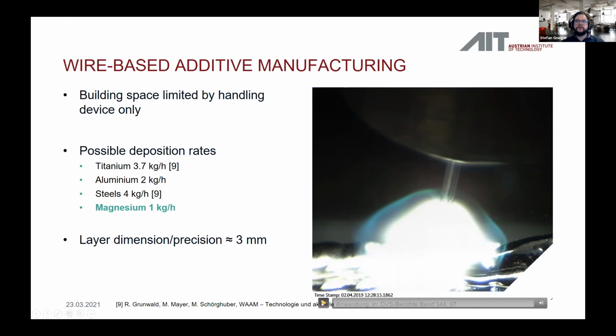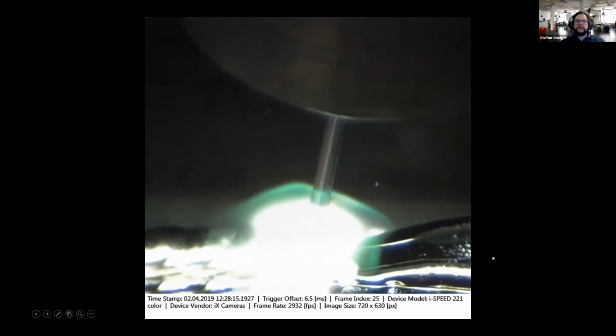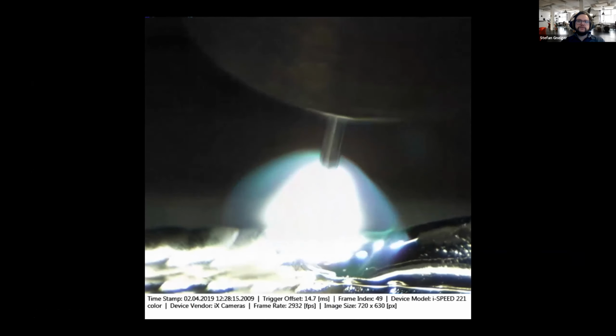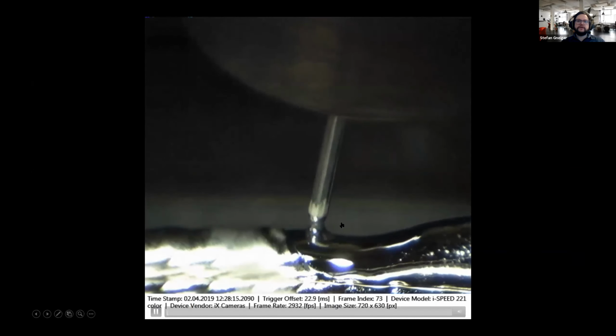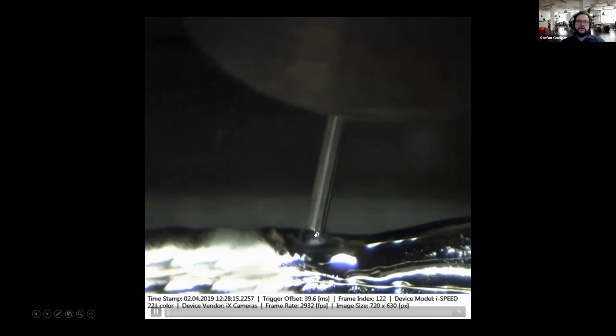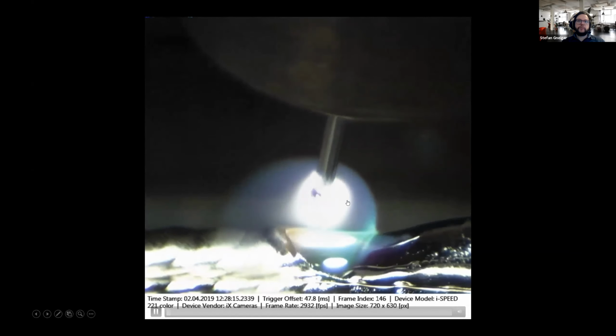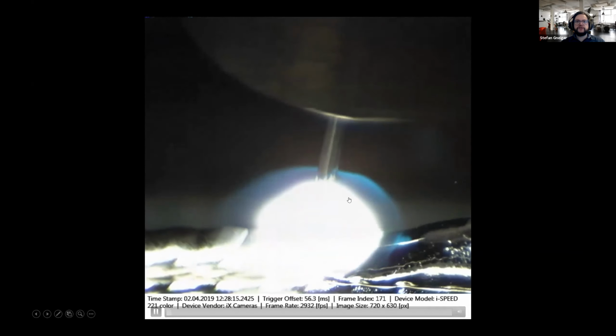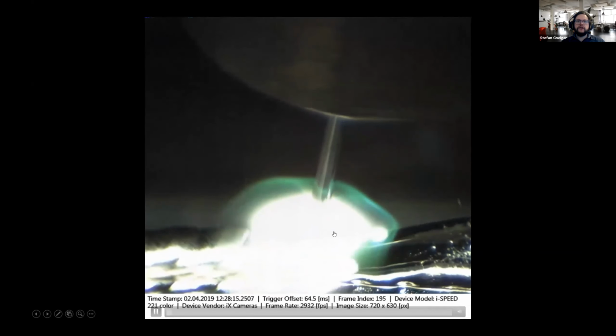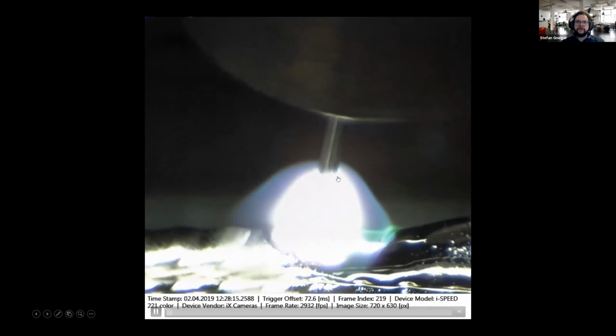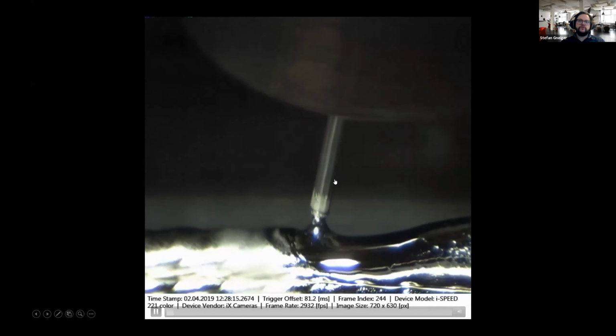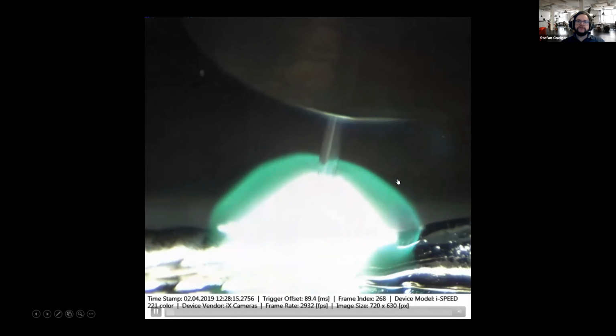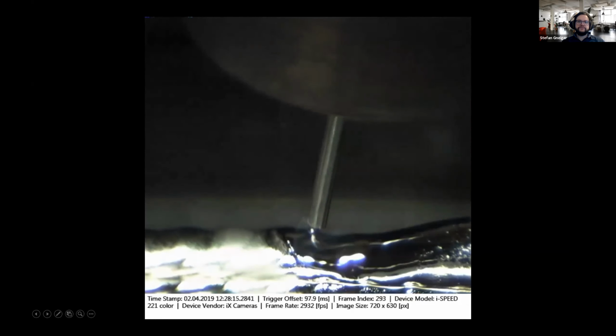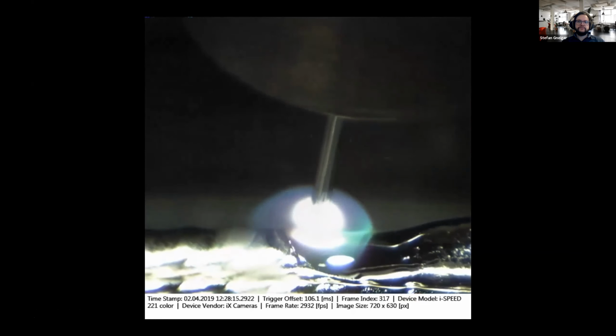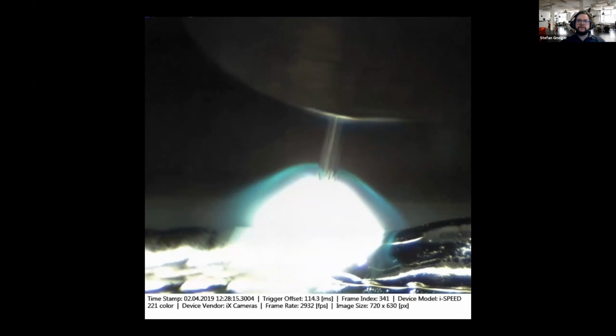I will show you a short video of the cold metal transfer process. As you can see, the wire is touching the part surface and the short circuit is formed. After this, the wire is pulled away from the part surface and you have this electric arc. And this high energy arc melts the wire on the tip. And by the forward movement, this molten droplet is placed on the part. So it's layer by layer and small droplets.